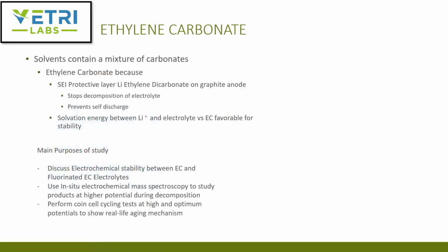Why ethylene carbonate? The electrolytes contain a mixture of carbonates. Ethylene carbonate is preferred because it forms a protective layer on the graphite anode and stops decomposition of the electrolyte. It prevents self-discharge, and the solvation energy between the lithium plus and the electrolyte, with LiPF6 and ethylene carbonate, is favorable from a stability standpoint. These are the main reasons why they contain ethylene carbonate.